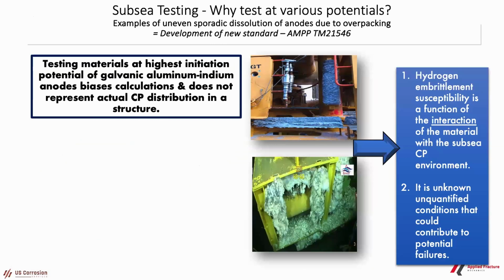And so this is an example of why this testing is important. When you're looking at cathodic protection, especially when you're using anodes, you find that depending on how the anodes are loaded, you might end up with some anodes that are almost completely depleted after 20 years, other ones that never even activated correctly or have calcareous growth that's causing problems with it. And so that was part of what also pushed us to do more of this research and development.